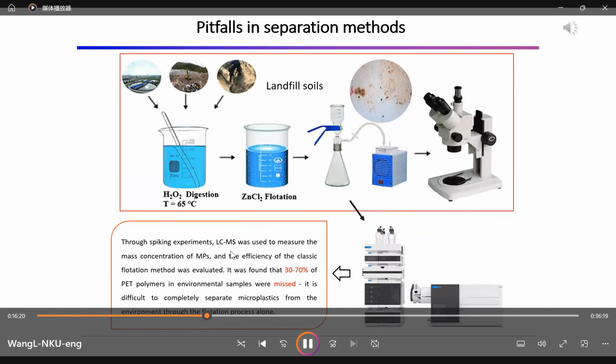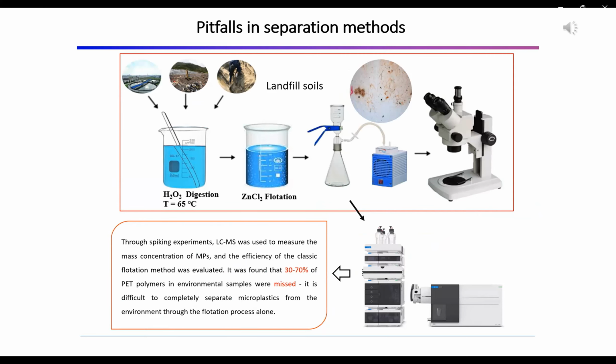We tested the efficiency of the commonly used flotation separation method. LC mass was used to measure the mass concentration of microplastics in the floated part and the residue part of soil samples collected in a landfill site, and the efficiency of the classic flotation method was evaluated. It was found that 30% to 70% of PET polymers in the environmental samples were missed. Therefore, it is difficult to completely separate the microplastics from the environmental samples through the flotation process alone.